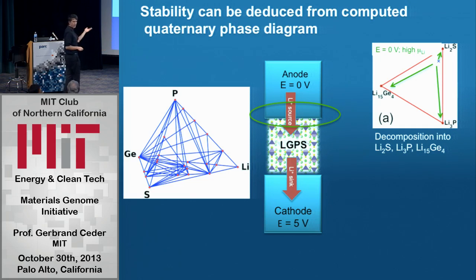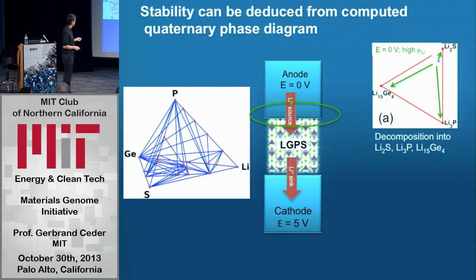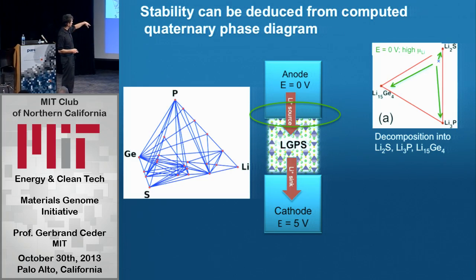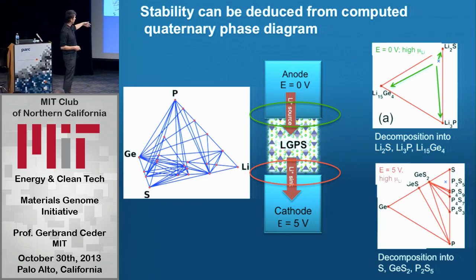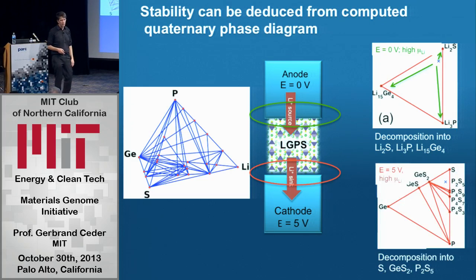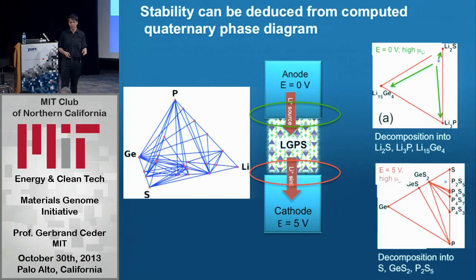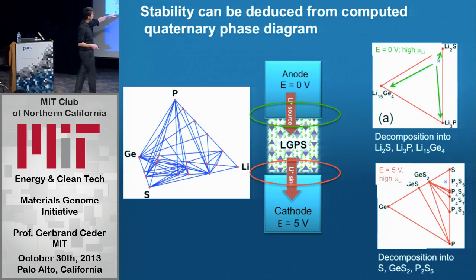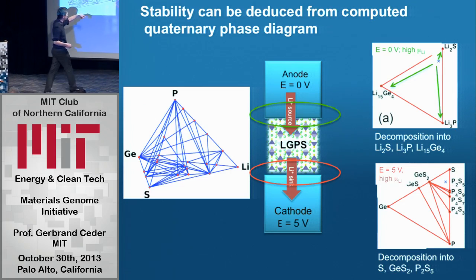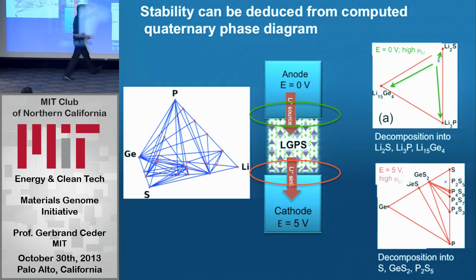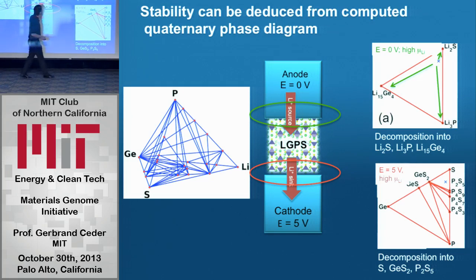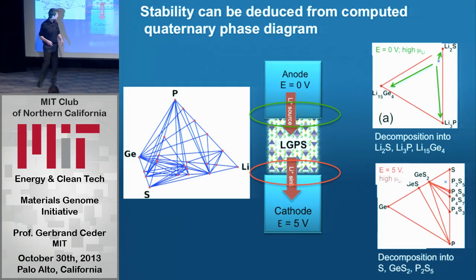So a lot of things break down. That's part of the problem. So to look at actually what happens to this conductor against the anode and cathode, we actually calculate phase diagrams. And what we predicted computationally is that this material would not be stable against the electrodes. That's not necessarily bad news. It just means you have to do stuff. So we predict that on the anode, it would decompose into these 3 compounds here. And the problem is this is a metal, and that sends your electrons through the electrolyte, so that's bad news.